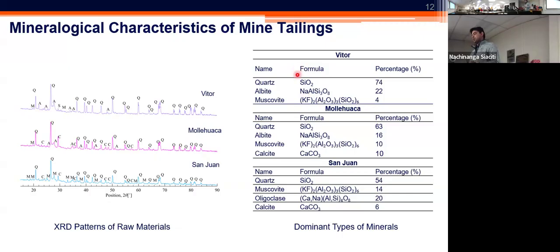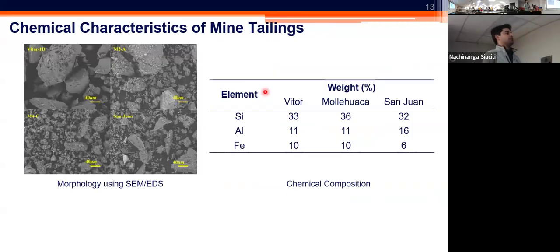In these samples that we had a chance to work with, we identified quartz as the dominant type of crystal. In addition to that, we also had albite and muscovite that were rich sources of aluminum oxide as well as silicon dioxide. In terms of the elemental evaluation, you also can quickly reveal the elemental composition by doing basic scanning electron microscope imaging with the EDS. So this would not only reveal the morphology of the grains, but also surface-based elemental composition of these types of tailings. So in the tailing samples, again, that we had a chance to work with, we often saw that we commonly had silicon, aluminum, and iron as the dominant types of elements that were available.